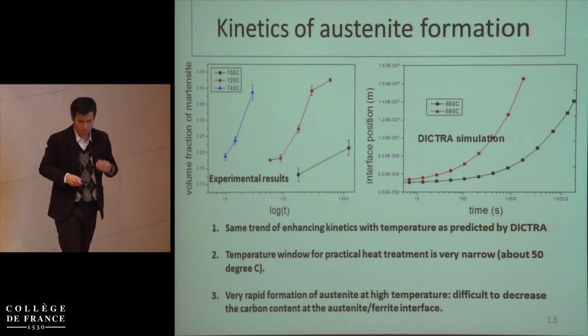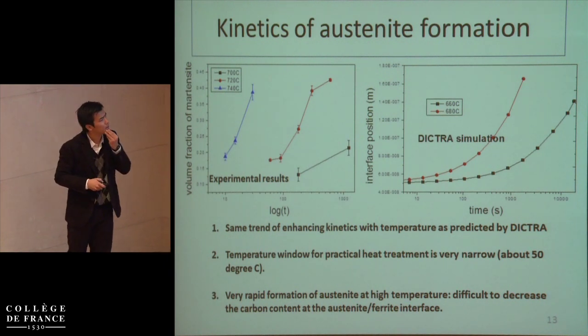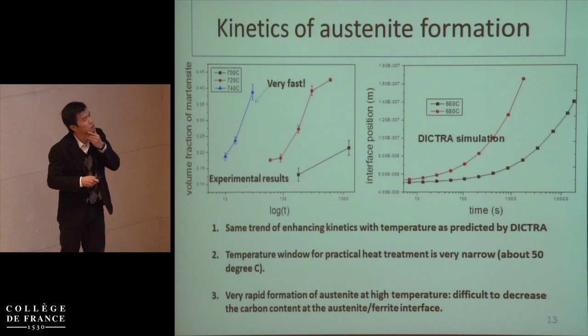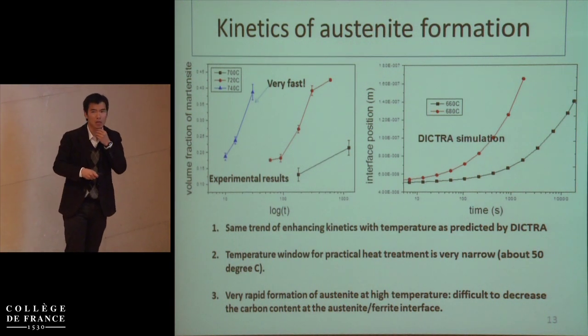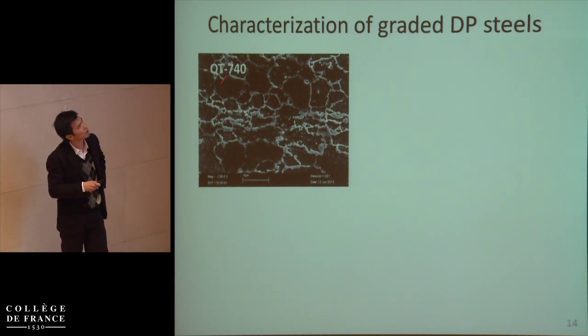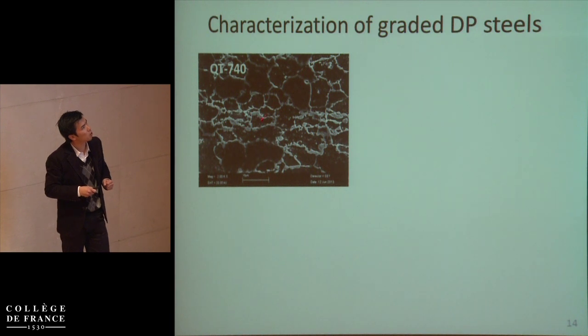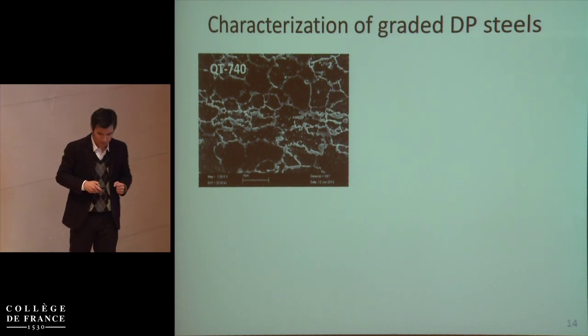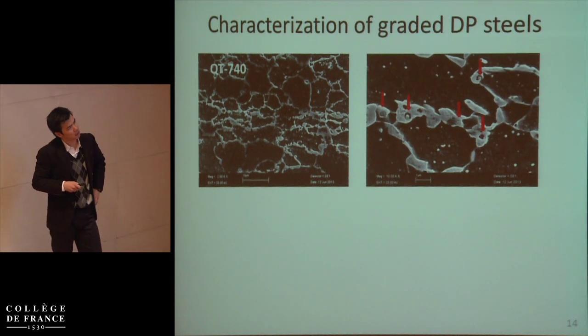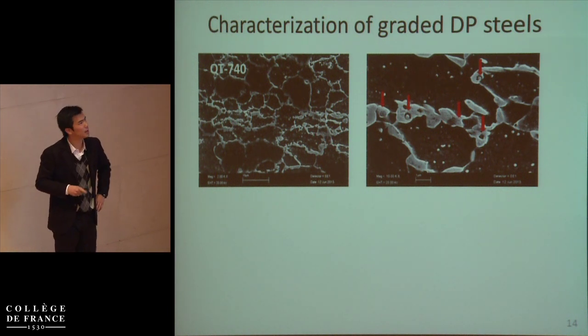Remember that we increase the annealing temperature to decrease the carbon content at the interface, but austenite formation at high temperature is very fast — this sets an upper limit in our practical trial. I characterized the microstructure annealed at 740°C: with a relatively small volume fraction of martensite, the martensite islands are distributed along the ferrite grain sites like a necklace. With larger magnification after light etching we can see very clearly the features of retained austenite within the martensite.